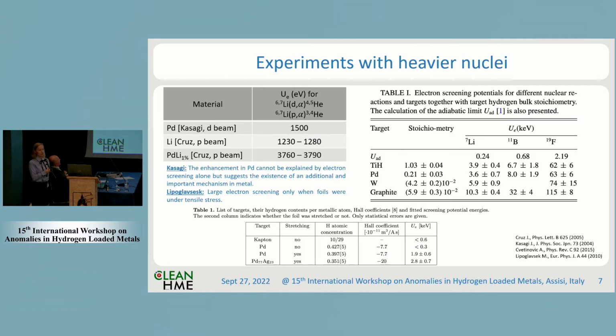Okay, and there have been some other experiments. I call them here the heavier nuclei experiments. So you can see an experiment on lithium with deuterons or lithium with protons. Okay, so the two kinds of reactions, I have here 6 and 7 because in natural lithium there are two isotopes involved. So the first material was palladium. This was done by Kasagi with the deuteron beam, and the value arose to 1,500 electron volts. So this is crazy high, let's say. Okay, but these experiments were really well described in the paper. Okay, again, the paper is given over here.